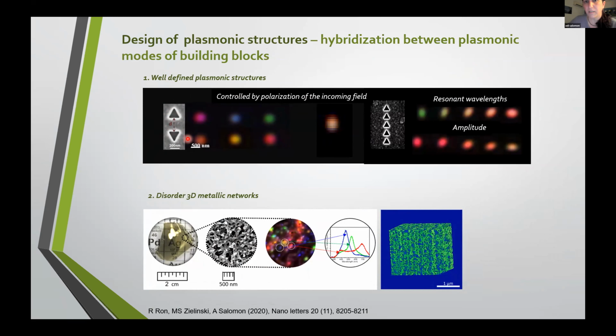Again, the idea is to use a well-defined plasmonic structure to harness the electromagnetic field at different frequencies, and to control it by either the polarization of the incoming field or the distance between these holes. We can control the frequency, as you can see in this example, but also, by changing the parameters of the subunit, which is just a single triangular hole, we can also control the amplitude. What you can see here is an example of the metallic network. This is cathodoluminescence scanning, and you see that it has multiple hotspots at different wavelengths at sub-wavelength distances as well. So basically, it's a sponge of hotspots.